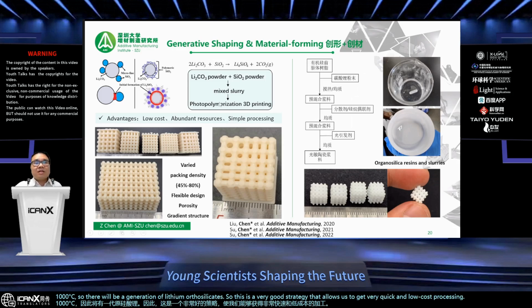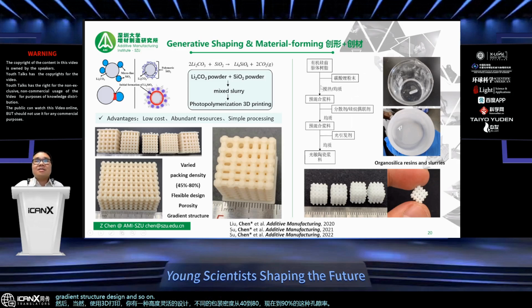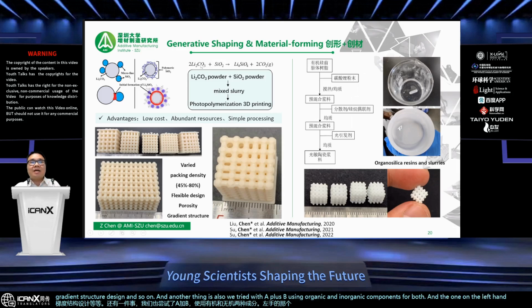Then, of course, using 3D printing, you have a highly flexible design, varied packing density starting from like 40 to like 80, now to 90% for this kind of porosity, gradient structure design, and so on. Another thing is we also try A plus B using organic and inorganic components. The one on the left hand side is A plus B, they are inorganic, and we have inorganic plus organic as well. Both routes are feasible and they are working quite well.